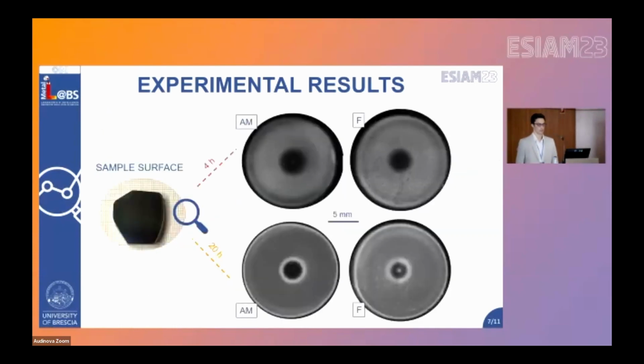In addition, at every test interruption, images by stereo microscope were taken, and you can see in the top there are the image of the sample at 4 hours. Actually, the light gray shade that you see is not a loss of material, but it's just a micro deformation of the surface, since at 4 hours there was no actual mass loss recorded.